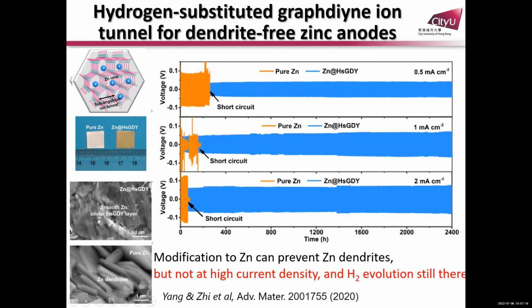This is a new material. I've been thinking about these materials for a pretty long time. Usually we synthesize these materials using copper as a catalyst, but in our lab we have a lot of zinc. When we were trying to synthesize these materials, we noticed that if you put zinc in the solution, you also synthesize graphdiyne on the surface. You see the color change. Graphdiyne has a channel structure, so it redistributes the zinc ions. In the symmetrical battery with the coating, the blue one, you get much better stability, although the current densities are not that high.